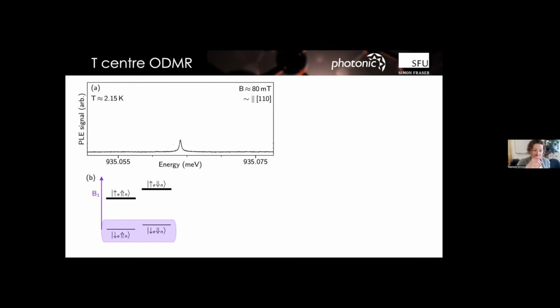Right, so what you can do when you drive it resonantly is very, very quickly hyperpolarize it, right? So if you drive one of those optical transitions, here with the B transition, you're of course driving both of the nuclear spin states within that because you can't optically resolve them. So they're both getting pumped to that TX naught state, and it's coming right back to the other electron spin state. It actually could come back to both. There are branching ratios, but very quickly it hyperpolarizes.